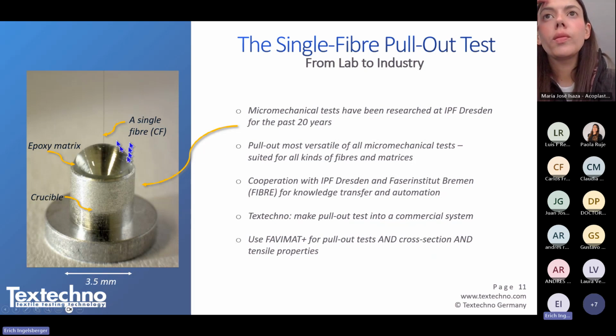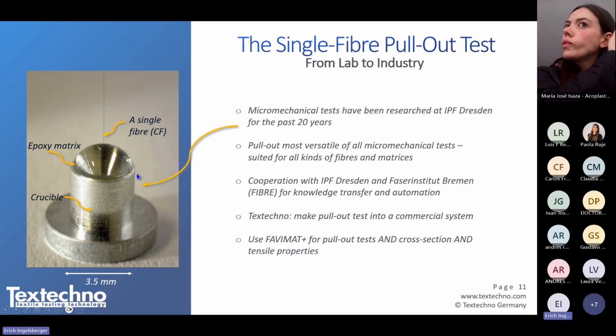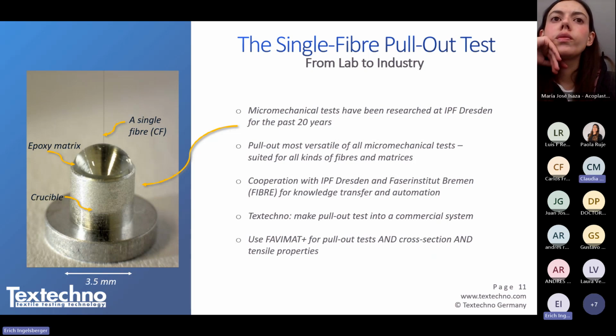This pull-out test of the drop of fiber is most versatile. We can do this test on any type of fiber - glass fiber, carbon fiber, natural fibers or synthetic fibers, any kind of fiber. We can also use any type of matrix. If we use a thermoplastic matrix, we could even go to higher temperatures than 400 degrees, meaning we could also process PEEK as the matrix.